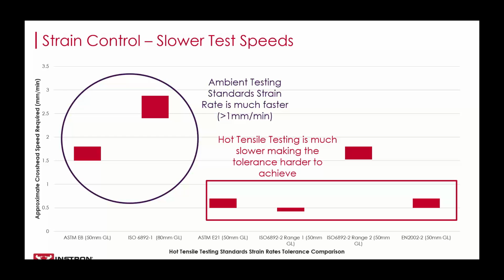Now, across both standards, we see that elevated temperature testing occurs at slower strain rates, typically 0.005 millimeter per millimeter per minute. It's a little difficult to visualize what that means in terms of controlling the frame, though. So we've created this diagram here where we take the target strain rate for various tests and convert that into allowable crosshead speeds for those tests.